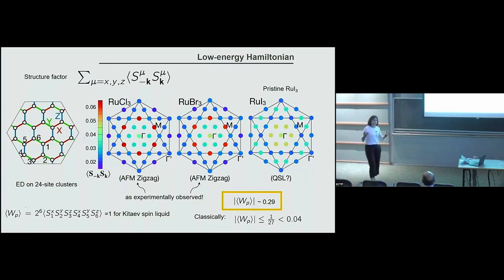It could well be that it is due to the finite cluster not being big enough, and there could be Q vectors that are not in the cluster. But it could also be a hint that these longer range Kitaev interactions are inducing a spin liquid. But it would be a spin liquid of a different kind to the Kitaev spin liquid. So for the Kitaev spin liquid, we can use this plaquette operator. We know that the plaquette operator is equal to 1. So we use this plaquette operator as an order parameter to see how different from 1 it is for this ruthenium iodide.